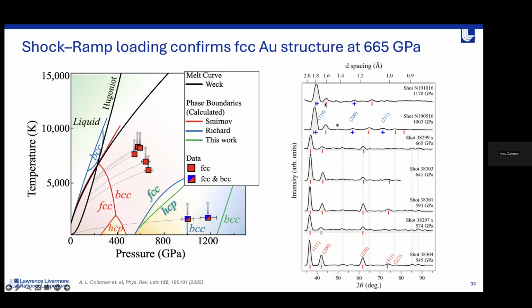We can see these red tick marks are indicative of FCC peaks, and these blue crosses are our BCC peaks here. To bring our story to a close, looking at these shock ramp compression data, you'll notice that all of the squares are red. That is because all we saw in this regime was FCC gold - there was no indication of BCC gold.